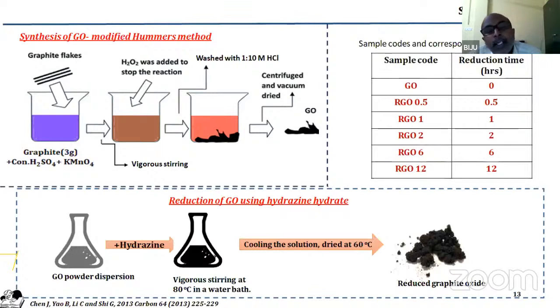And then we have reduced this graphite oxide using hydrazine hydrate as a reducing agent. So it was an aqueous solution-based reducing technique to obtain reduced graphite oxide. Now we changed the time of the reaction to obtain different levels of reduction. 0 was the starting material, and the reduction time was changed from half an hour to 12 hours. The sample codes are 0.5 meaning reduced for 30 minutes, then 1 hour, 2 hour, 6 hour, and 12 hour, and so on.